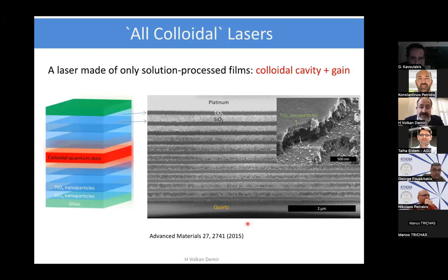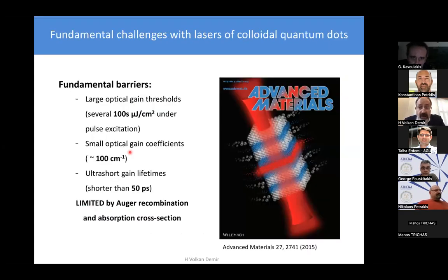And in the similar times, in an independent project, we have been trying to push the lasing behavior using colloidal quantum dots as opposed to wells, using, again, this all colloidal laser architecture that I showed you, where the Bragg reflectors are also made of colloidal materials. In this case, titania and silica, titanium dioxide and silicon dioxide, as alternating layers, spin coated to create the Bragg reflectors, and then using pair of them to sandwich our gain material. And no matter how hard we looked into engineering the material, or the optical architecture, we always hit the limits.